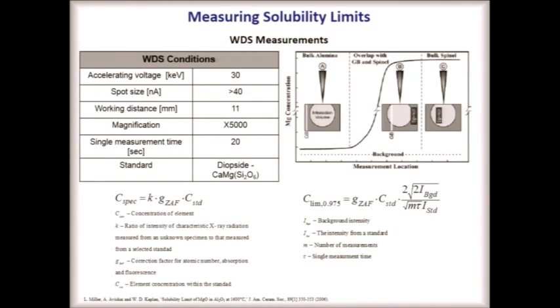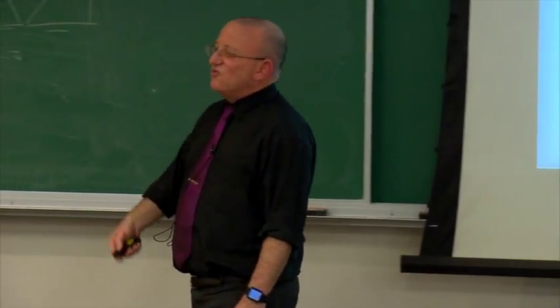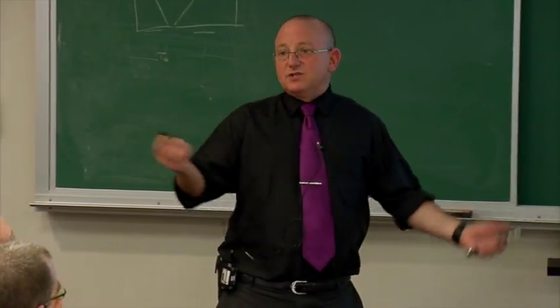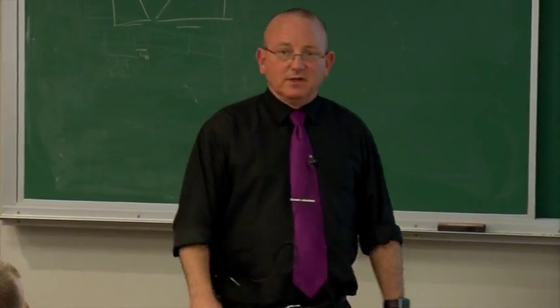This is my electron beam and it's interacting, this is our interaction volume, and this is the alumina grain. If we measure it and it's just in the alumina grain, then obviously we're going to get a number which fits the solubility limit for the specimens I just described. If this interaction volume overlaps with the grain boundary, where there might be an excess, then it's going to go up. Or if it overlaps with a precipitate, then it's going to really crank out. And we're going to get numbers which are really, really high. So if we just go in and do literally hundreds and hundreds of measurements, we'll get a histogram. And we should be able to see the distribution immediately.